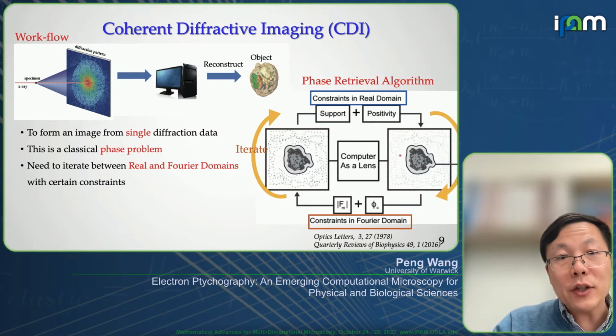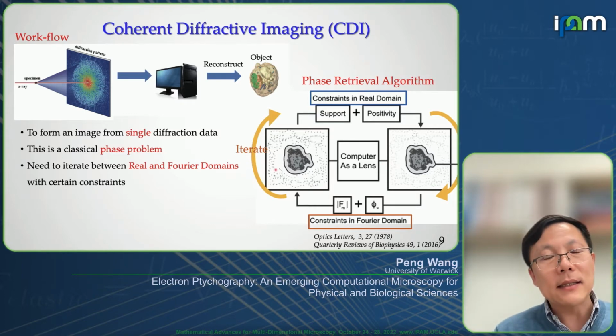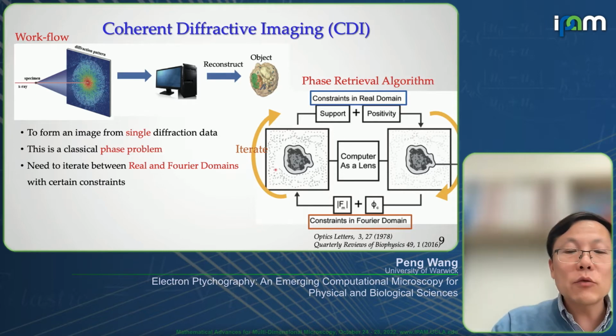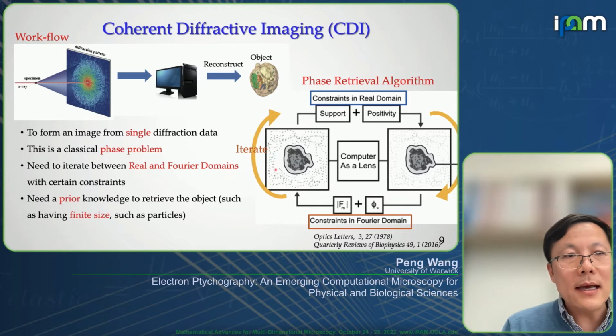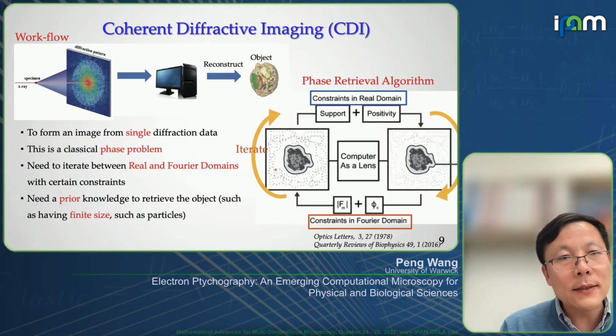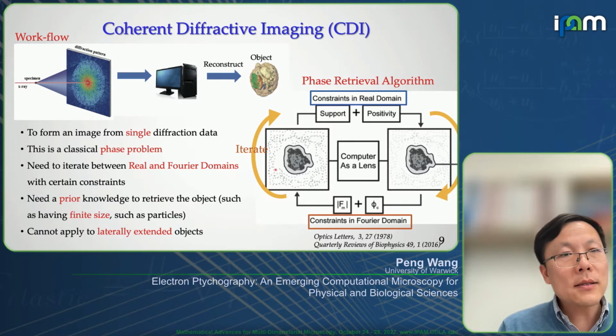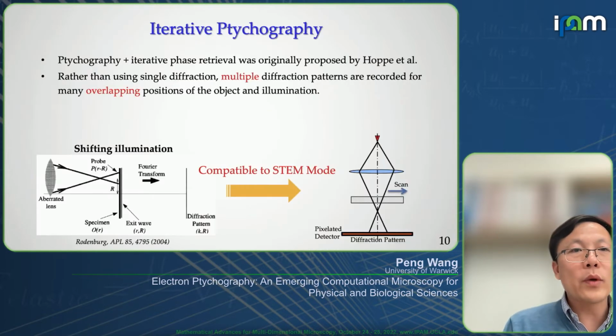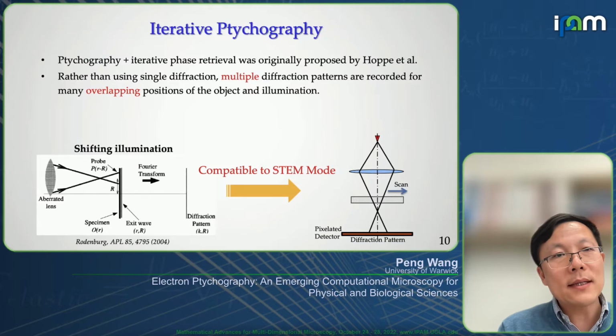One constraint in the diffraction domain is the measured intensity of the diffraction pattern. In real space, what we normally use is a finite size, such that the sample has to be a particle with a support around it, which maybe can be a vacuum. So you will find this method is very useful for nanoparticles, but it has difficulty applying to laterally extended objects. Therefore, we would like to investigate that using iterative ptychography.